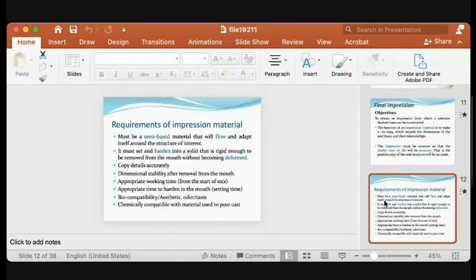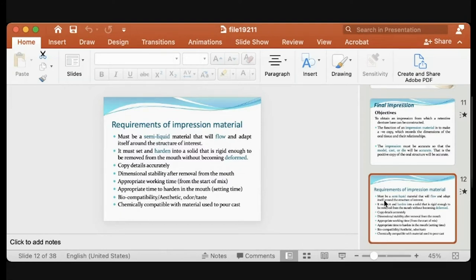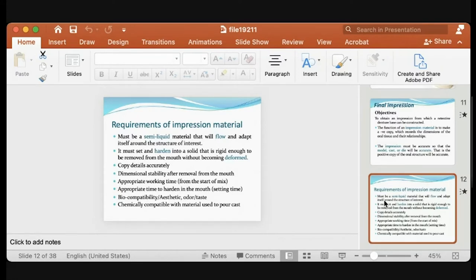For example, if you mix alginate in a too-fluid way, when you put it in the tray it flows away with no registration of anatomical landmarks. If the material is too hard, it cannot adapt to undercuts or fine tissue details. The semi-liquid material gives you good flow and good adaptation around all the structures you want to record. It must then set hard and rigid enough to be removed from the mouth without deformation or destruction.